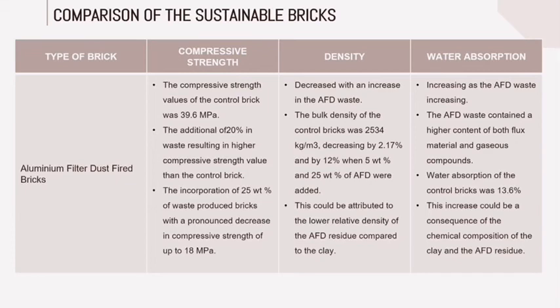The compressive strength value of the control brick was 39.6 MPa. The addition of 20% waste resulted in a higher compressive strength than the control brick, but the incorporation of 25% waste produced bricks with a pronounced decrease in compressive strength, down to 18 MPa.